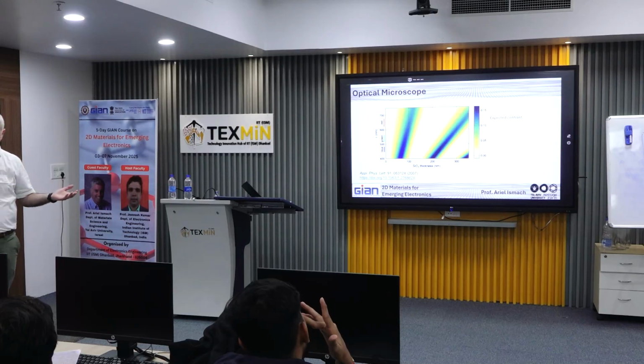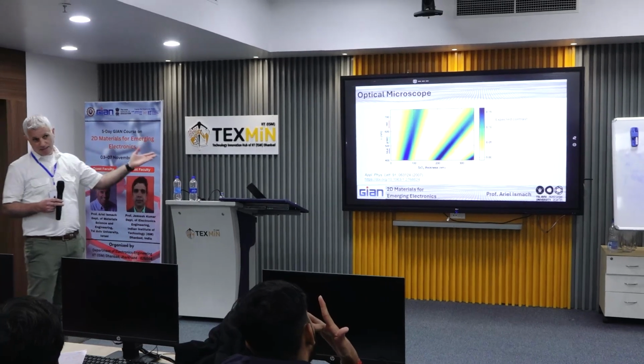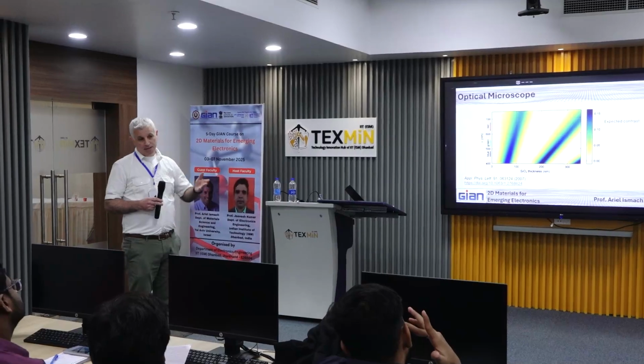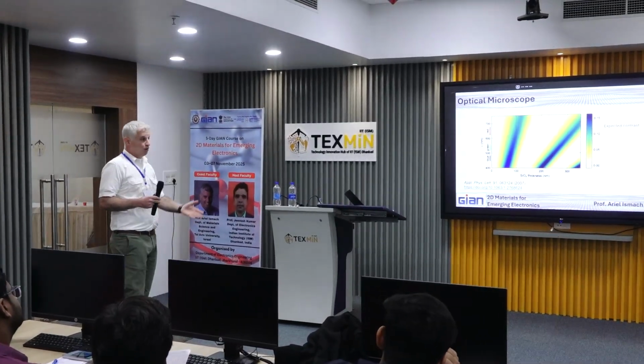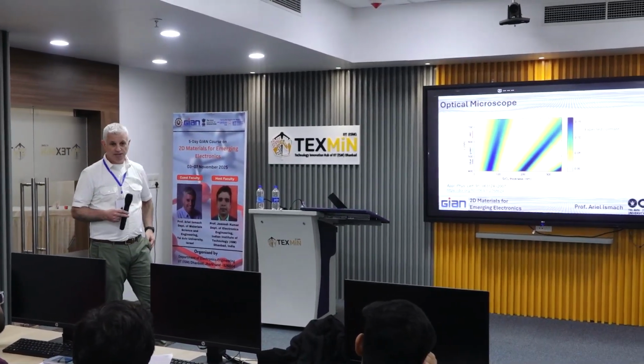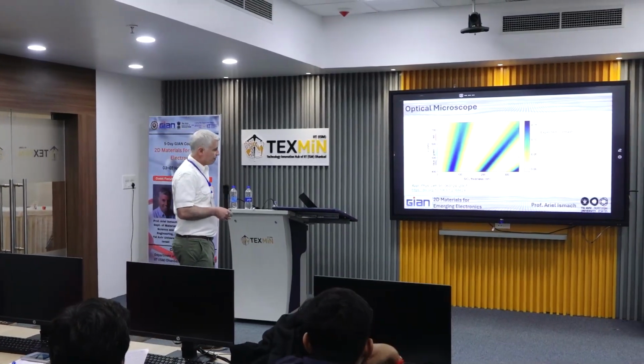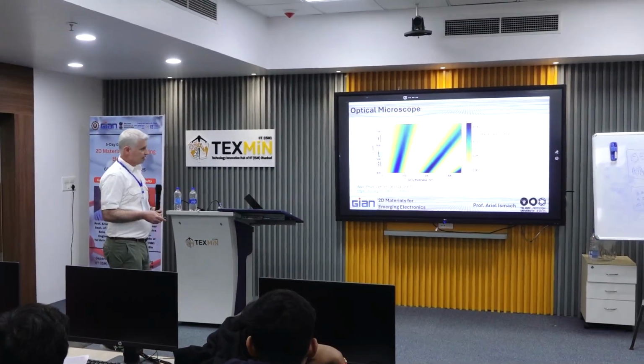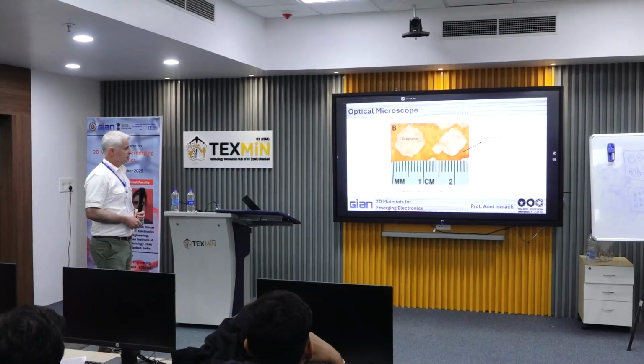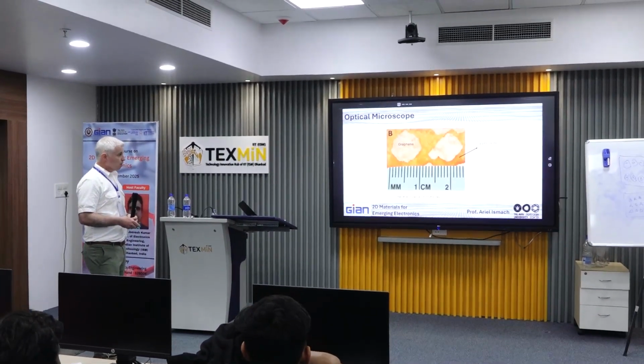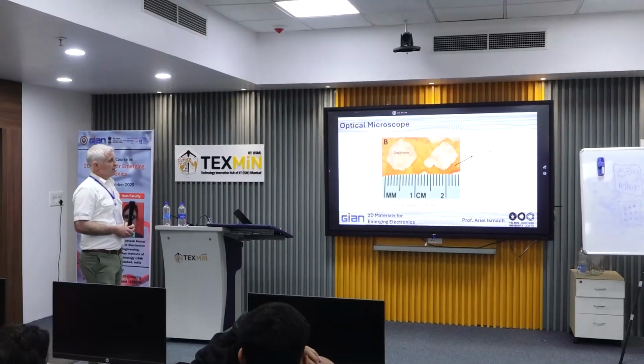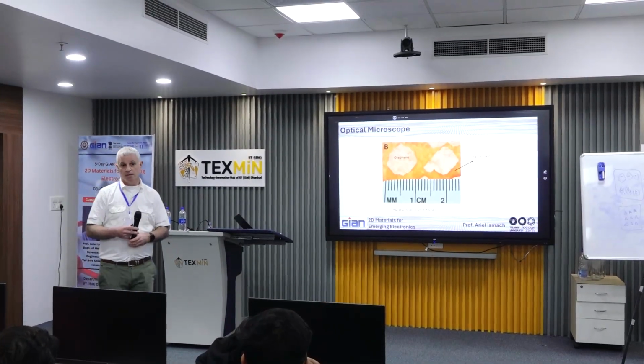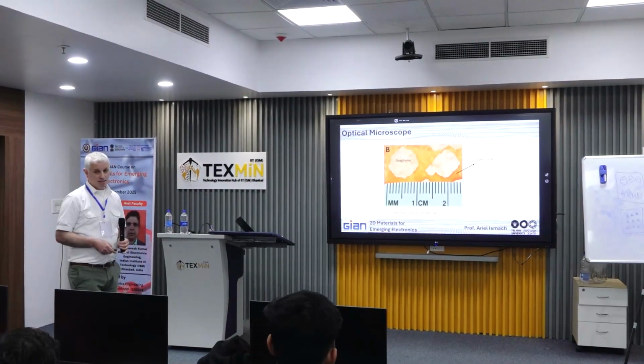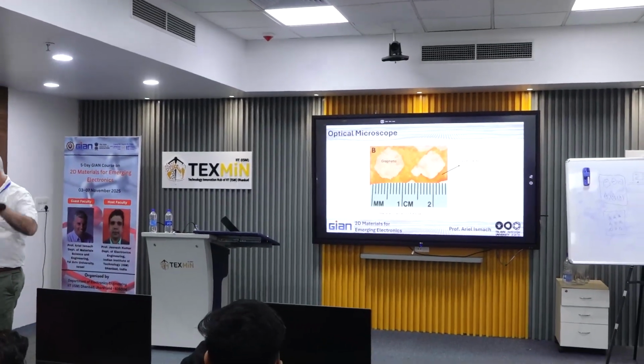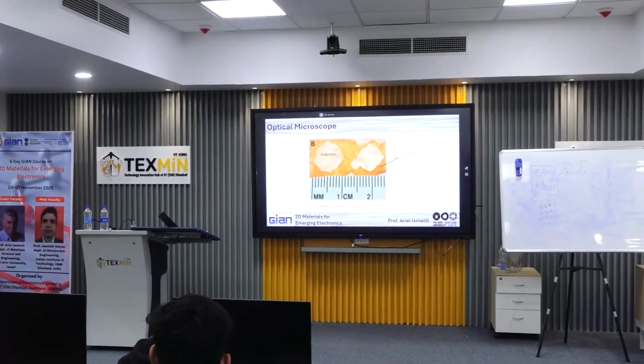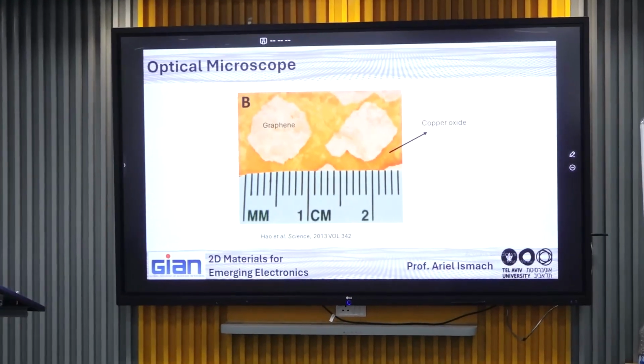Let's say that you're looking for a single layer. You can look for the single layer in the optical microscope, and if not, then you make another exfoliation. Okay, so this is very fast, very convenient, and that's why it's very common, and that's why it was so heavily analyzed. So what happens when we have a different substrate, right? This is on silicon dioxide silicon, which is okay, and we saw the contrast behavior. What happens when we do that on a different substrate?